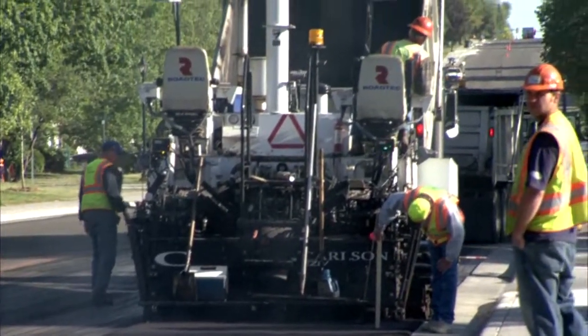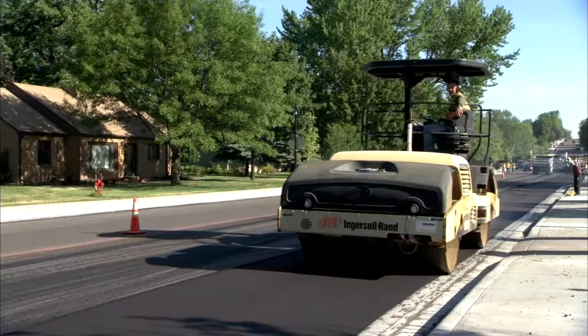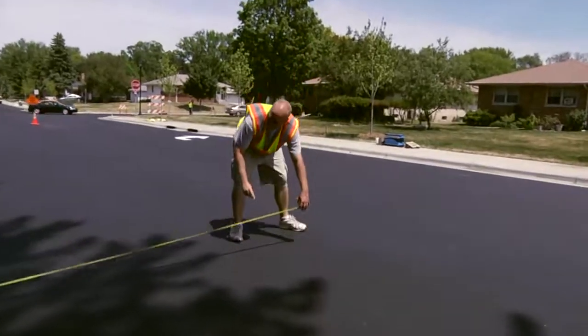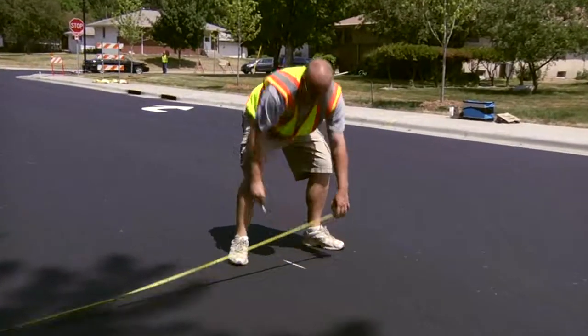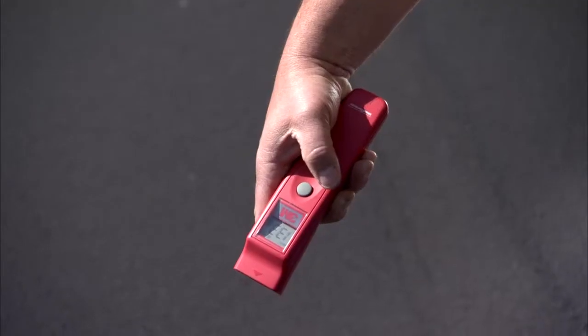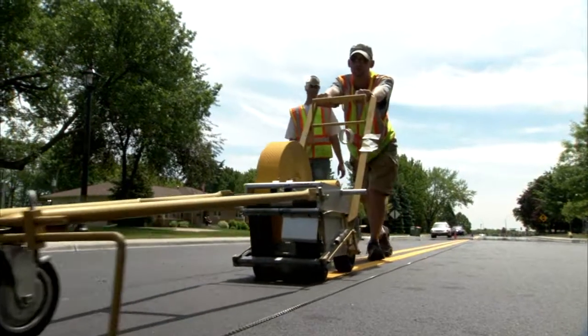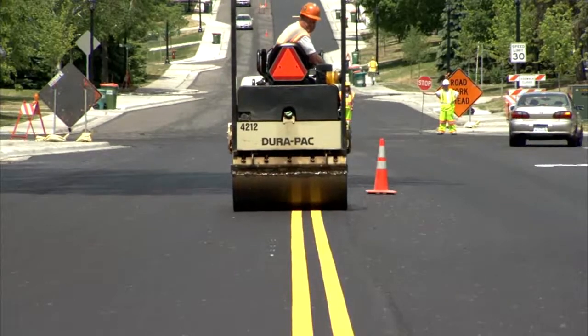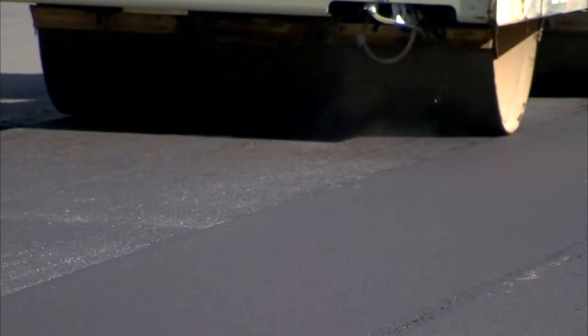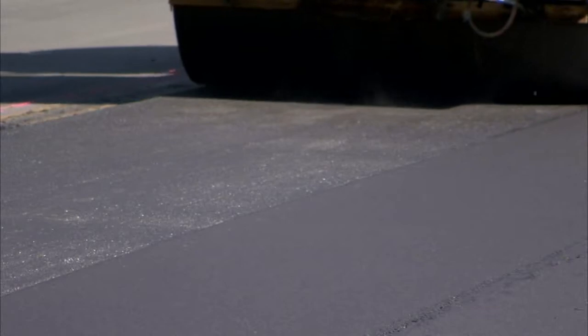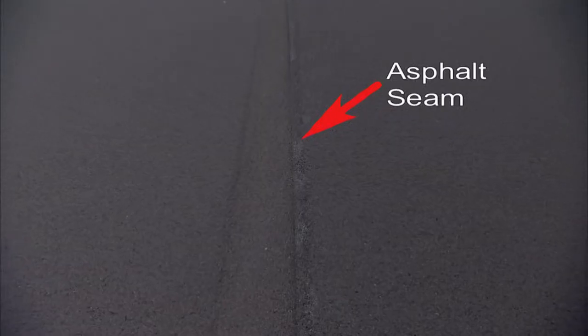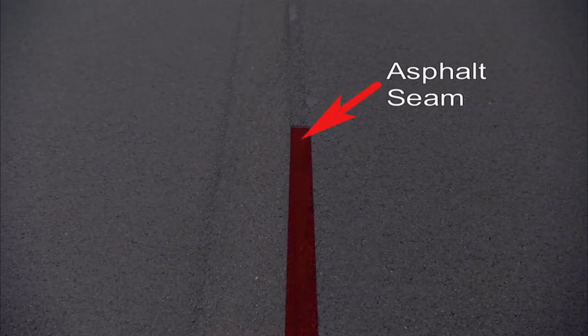Inlay process steps include paving and compaction of the fresh asphalt, pre-marking the road, testing the asphalt surface temperature, applying the tape, and inlaying the tape into the pavement. The process begins with a freshly paved and compacted lane surface. Lanes should be paved so the tape is not placed on asphalt seams between lanes.